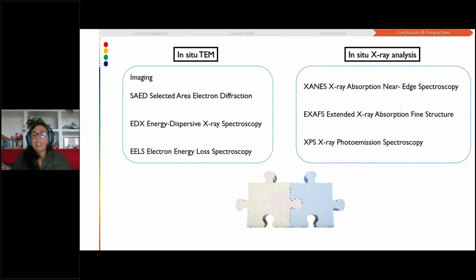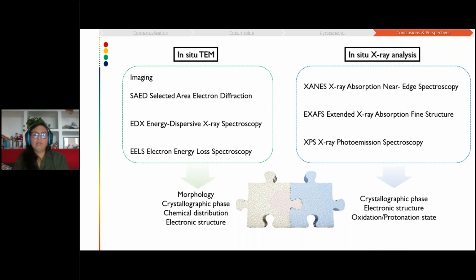And finally, I would like to show a perspective. This is the idea I have had since the beginning of my PhD: the importance of using different operando and in situ techniques to complement the different studies that we perform. In situ TEM gives us information about the morphology, the crystallographic phase, the chemical distribution, and the electronic structure at the atomic or particle scale. But in situ X-ray analysis can give us crystallographic, electronic, and oxidation state information at the macro scale in a very local environment.